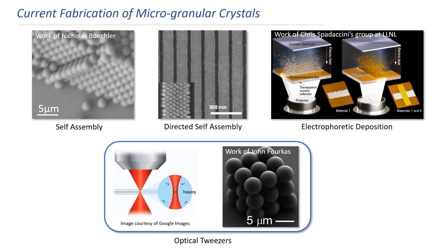Other researchers have proposed using optical tweezers to overcome the inflexibility of these fabrication approaches. Optical tweezers are tightly focused laser beams that leverage electric-field gradients to optically trap tiny particles near their waist. By steering the laser's focal spot, individually trapped microspheres can be moved to desired locations within a lattice. When the spheres arrive at their desired location, the optical tweezers can immediately release their spheres without perturbing their locations with attractive intermolecular forces inherent to micro-scale mechanical tweezers alternatives by simply turning off their laser. The impressive 3x3x3 lattice shown in the SEM image here was fabricated using this approach in John Fourkas' lab at the University of Maryland. A student manually used a single optical trap to assemble this crystal individually one sphere at a time. Although this approach is sufficiently flexible to fabricate engineered crystal lattices, the manual assembly of such crystals is extremely time-consuming and is prone to stack-up errors from human imprecision, which limits the size of the crystals that the approach is able to produce.